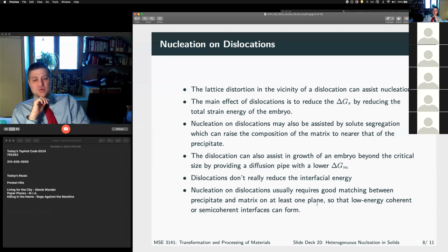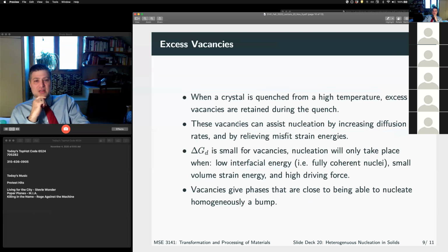A dislocation won't help us nucleate really large particles with a huge strain and a large interfacial energy. But they will really help us nucleate intermediate phases that have a lower energy, right? And the strain term and the little bit extra diffusion that we get means that everything is going to nucleate at a dislocation, right? Because of that small energy bonus, right?